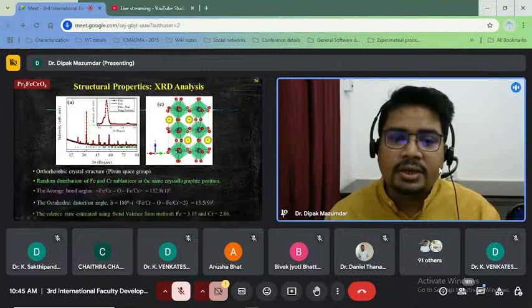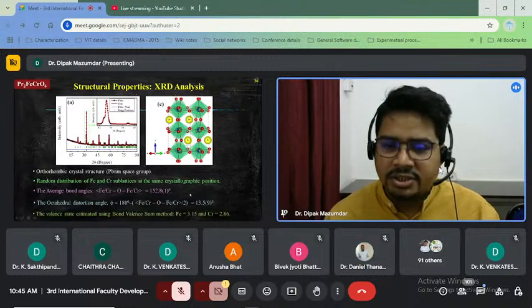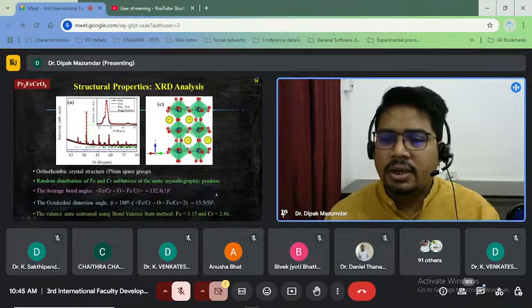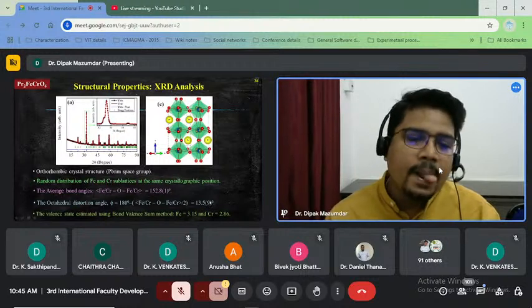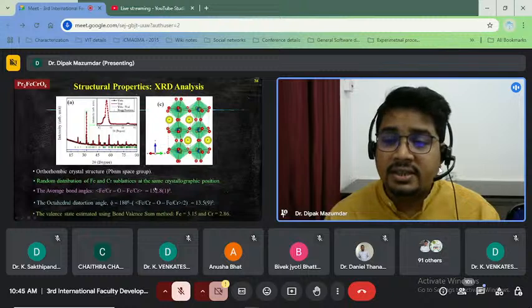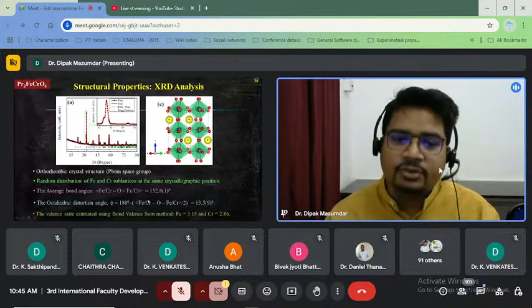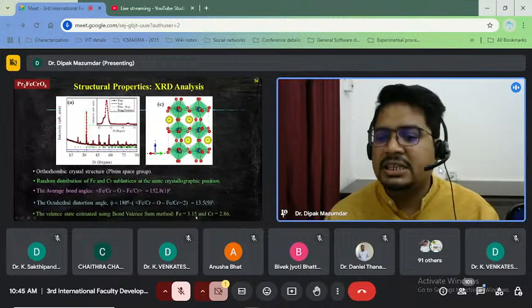This represents the occupation of two different atoms in the same crystallographic position. And we have also calculated the average bond angle and octahedral distortion like earlier cases. Here it comes around 13.5 degrees. And we also estimated the bond valence. We have estimated the valence state of these two ions, iron and chromium, which is approximately nearly 3.